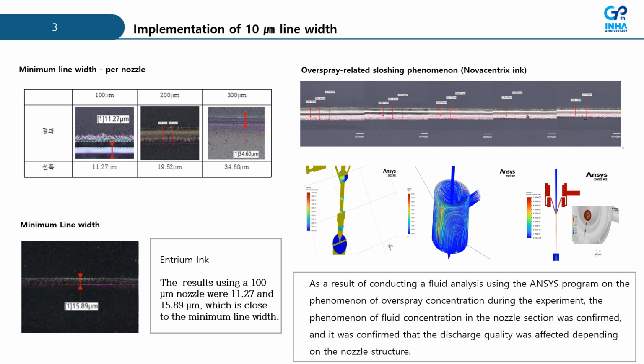We conducted tests on nozzles of 100, 200, and 300 microns, and the results of ejection using a 100 micrometer nozzle were 11.27 and 15.89 micrometers, which are close to the minimum line width of 10 micron. In the figure on the right, we found that the phenomenon of clouding due to overspray occurred not only in Inha University's machine, but also in the machines of other companies.